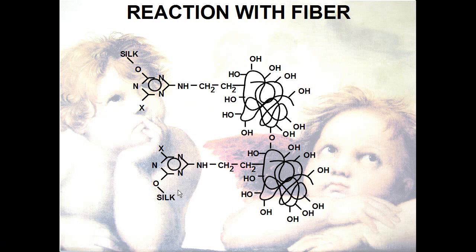How to fix it to the fiber? We should put in the polymer, choosing the right precursor, chemical groups that impart affinity to the fiber, or groups that are able to react with the fiber. Affinity means quaternary ammonium groups like softener. Reactivity could be epoxy group, could be triazinic group. The chemistry of triazinic group is well known from reactive dyestuff, and it is very interesting. And in this way, we can bond the polymer to the fiber. Here I write silk.